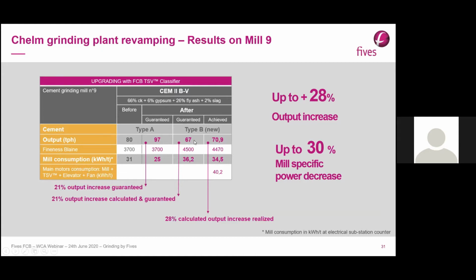Same ratio was applied for a new type of cement, which was not produced before by the client. We started from the assumption that the guarantee was 67 ton per hour, with 21% capacity increase guaranteed, and we reached 70.9 ton per hour during the performance test, meaning a 28% calculated capacity increase. Mill specific power consumption was decreasing in the same way, by up to 30%.